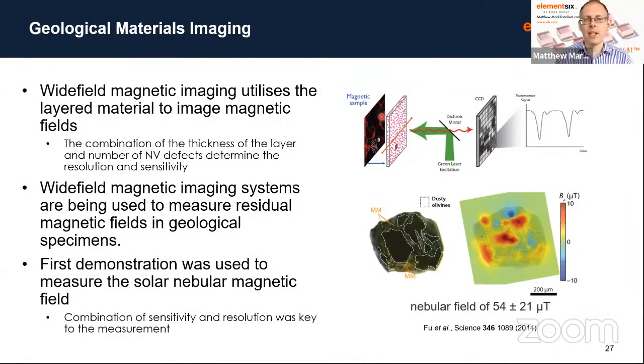And obviously in this particular application, the trade-off you've got is the thickness of that layer, which determines the NV concentration, but also determines the resolution. The thicker the layer, the lower the resolution, but the higher the sensitivity. So you've got this trade space that you've got to work with. What's very interesting about wide field magnetic imaging systems for geology is that you're able to measure the residual magnetic fields in geological specimens. This was some of the first work that Roger did when he was in Ron Walsworth's group, which was to measure the solar nebula magnetic field. This is the magnetic field that existed when the solar system was being formed. The reason diamond was key to this was that it had much higher sensitivity, but also the higher spatial resolution that you can get compared to other technologies.